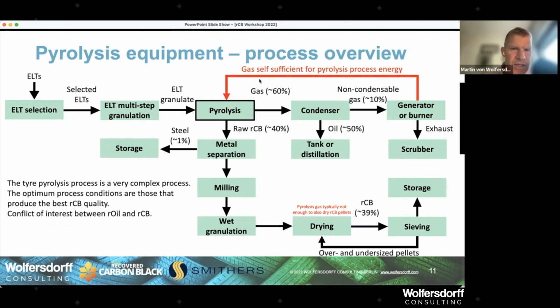In any case, that energy can be used for giving the energy for the pyrolysis. So most processes actually limit the gas mass flow to exactly what they need in the pyrolysis. It doesn't really make sense to sell the gas, but if you have surplus gas, you could use it also for drying the recovered carbon black pellets. Now, when we go to the raw recovered carbon black, the solid fraction coming out, which is about 40%, and these are typical mass fractions. Of course, if you run a higher temperature, you would get different things. Certain processes have different mass balances. So this is just a benchmark mass balance.